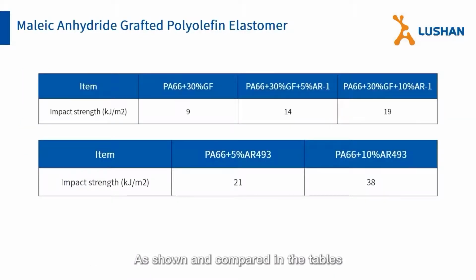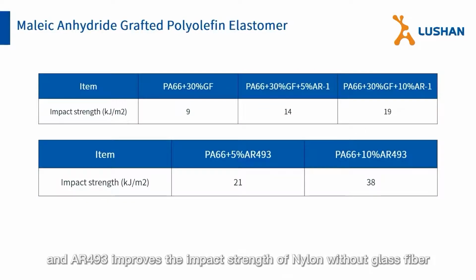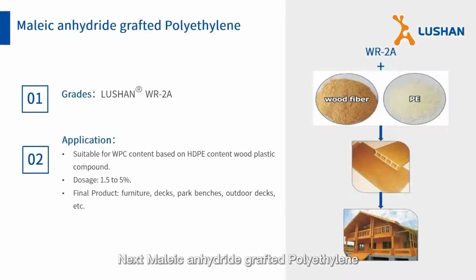As shown and compared in the tables, adding LUSHAN nylon impact modifier AR1 improves the impact strength of glass fiber nylon and AR493 improves the impact strength of nylon without glass fiber. Next, maleic anhydride grafted polyethylene is for wood plastic composites.